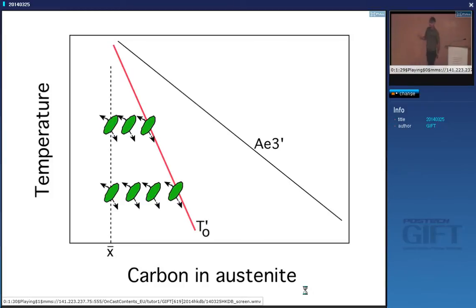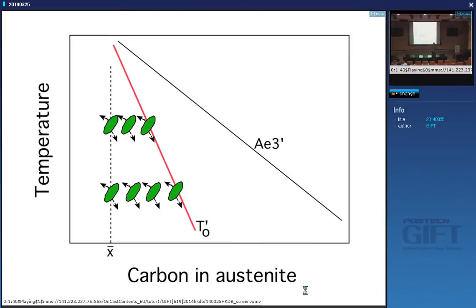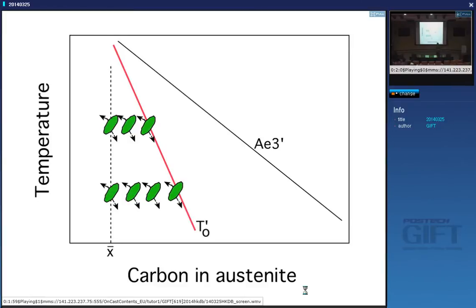We used that concept to show that the bainite transformation is diffusionless — it occurs without any chemical composition change, but it's happening at a temperature where carbon can diffuse out of the bainitic ferrite and deposit itself into the remaining austenite. So supposing I have a steel with a composition X-bar, and no other reactions are happening — for example precipitation of cementite is not happening — then I form a plate of bainite with the average composition of the steel, but it partitions carbon so the austenite becomes richer in carbon.